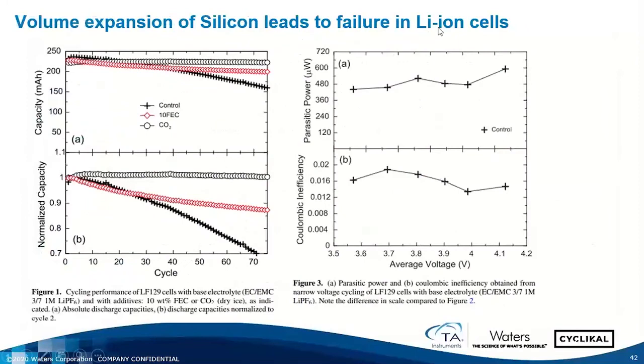All right, volume expansion of silicon leads to failure in lithium-ion cells. So the use of silicon is becoming more and more accepted in a number of different applications. And we've done a lot of work on this ourselves. This is a bit of a story about a lithium-ion full pouch cell, which has about 15 weight % of a silicon alloy. Now, it's not elemental silicon, but an engineered silicon. Silicon itself, when fully lithiated, can expand 300%, which is basically intolerable. So most efforts at including silicon have involved not elemental silicon, but an engineered type of silicon, so that the volume expansion is more akin to, say, 100%.